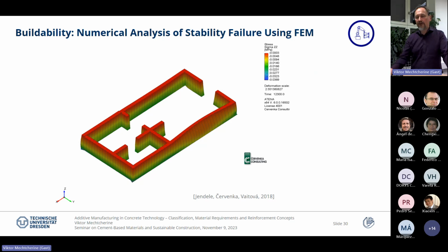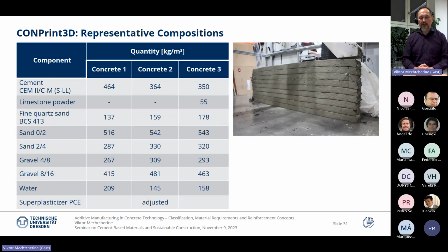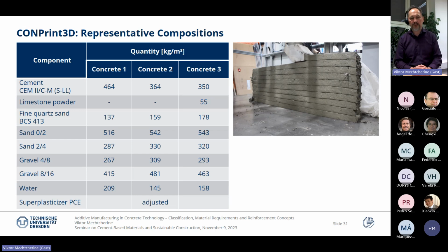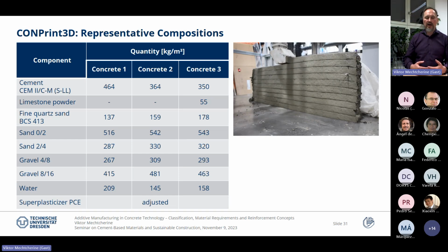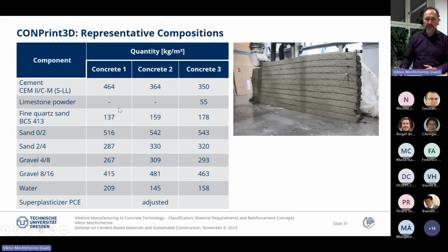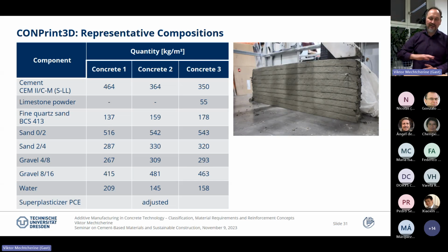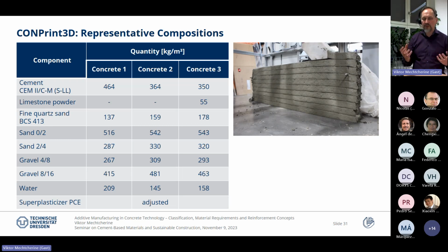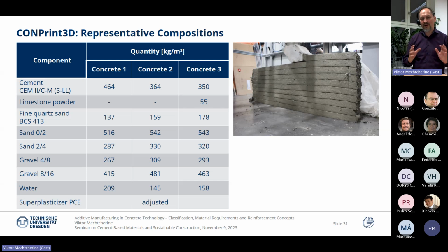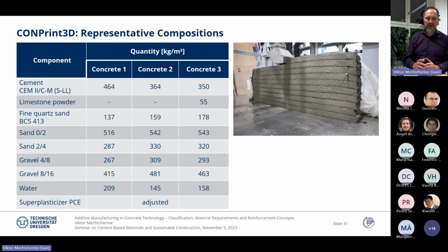Good. And then when you have a little bit more complex geometry than just a simple wall for which analytical formula are good enough, then again, numerical analysis is a good choice. In this case, a finite element method is quite a good choice. Good. If you ask what would be a recipe of materials we use for printing of this kind of walls for large filament printed, there are some examples. Actually, nothing fancy. We go up to 16 millimeters maximum aggregate size. So otherwise, what I want to emphasize that we need, of course, here quite a nice particle size distribution to attain also a good packing density, because it's a prerequisite actually for all concretes with well-controlled rheology.